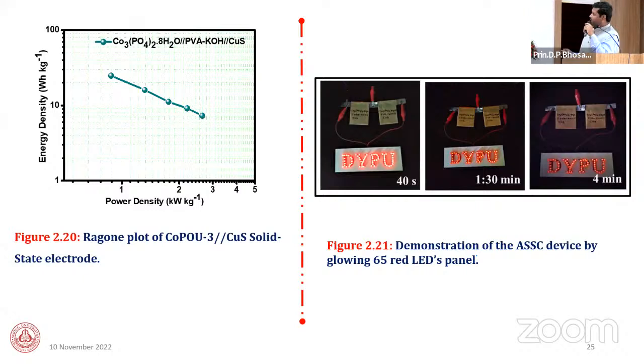And this is the practical device demonstration of this device using two serially connected devices charged for 30 seconds and discharged using this LED panel. This is the LED panel, 65 red LED panel for 4 minutes. And this figure shows this is the high intensity glow. It means high power density, for the 40 seconds is observed, and then it gives up to the 4 minutes. It gives high power density, energy density up to the 4 minutes.